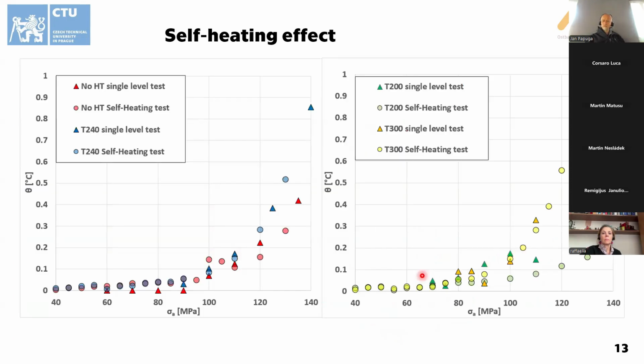As you can see, this is just to show you that the stabilized temperature for the single level test, by which I mean from the start of the testing to the failure of the specimen, is the same or similar to the one from the self-heating step test. And here we have a slight problem, I would say. For the T200 and non-heat treated variant, they follow a similar path, although it's not approximated by any curve right now. This can be said about the T300, but the T200 somewhat did not, and this is not really similar, and this is going to be visible for the fatigue life prediction as well.